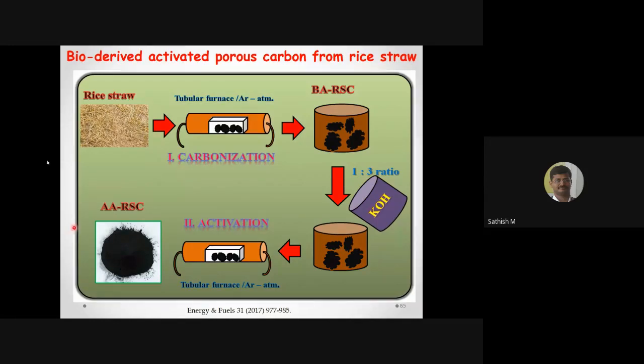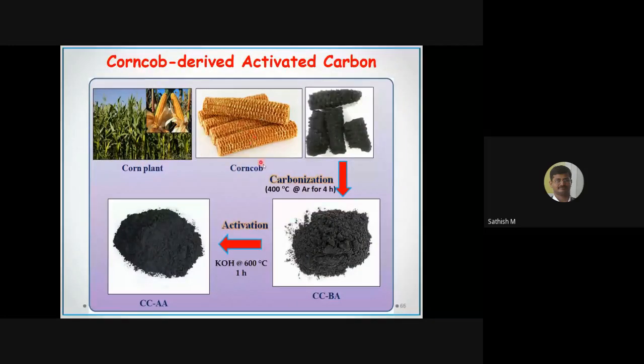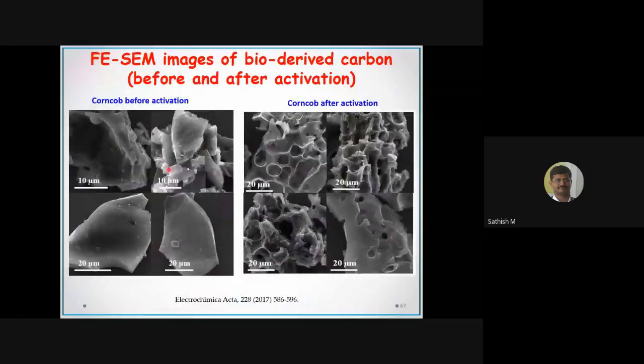We took some bio based material like rice straw or corn cob. We converted it into carbon based materials by using chemical activation. Okay, we end up with activated carbon. So these are SEM images of activated carbon before and after. Here you could see these are carbon blocks before activation. When you do the activation process, it makes a lot of punctures.